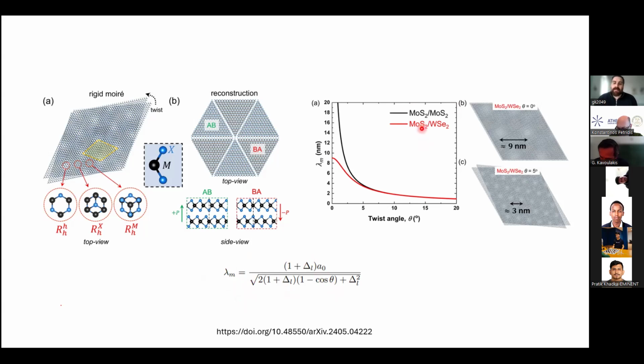And if we take a look at an example of heterostructures here, we compare a homobilayer, which is two same materials, and a heterobilayer, and we see that below 5 degrees of twist angle, for the homobilayer, the moiré periodicity goes to infinite, which is normal because if we have 0 degrees, we have a bilayer. We don't have a misalignment. We don't have a superlattice. And you can see here that by changing the twist angle, you can change a lot the moiré periodicity. And every time this happens, there is a huge effect on the properties of the heterostructures. An example is again the twisted bilayer graphene, where you have the magic angle of 1.1 degree, where you have the full effect of superconductivity. But if you slightly go away from this 1.1 degree, you will lose the superconductivity.